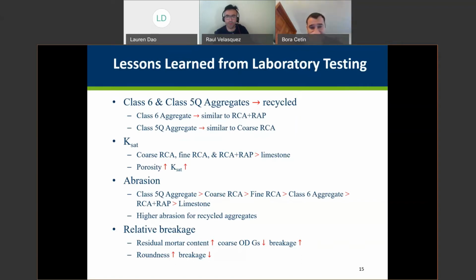And we will get to this a little bit, but fine RCA had a higher porosity than the coarse RCA, and we speculated that the porosity, of course, has a direct influence on the hydraulic conductivity, and as expected, materials that have higher porosity end up having higher hydraulic conductivity.